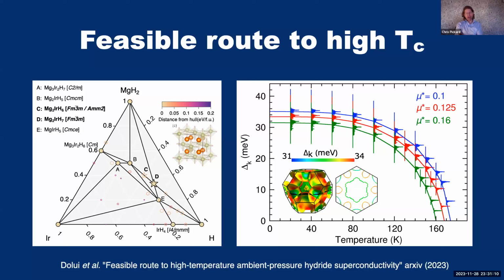So what I'm showing here is the result of this search. Obviously we found very large numbers of candidate structures, and what I'm showing you is the best one. The best structure that we came up with was Mg2IrH6 in a cubic phase, which is metastable at elevated pressures, but potentially offers a route to synthesis via very closely related stable phases.